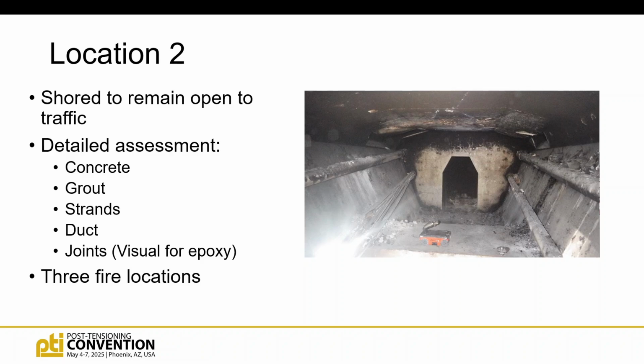And so this was one fire that got pretty hot. It didn't actually cause a lot of damage. The spalling in the concrete was minimal, was maybe a half-inch deep at the most. There was no tendons in this area. They all anchor way out here on the edges, so there was no damage to the tendons.